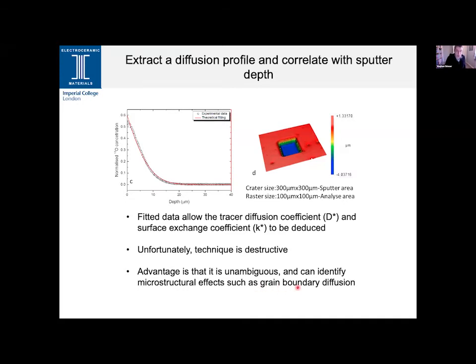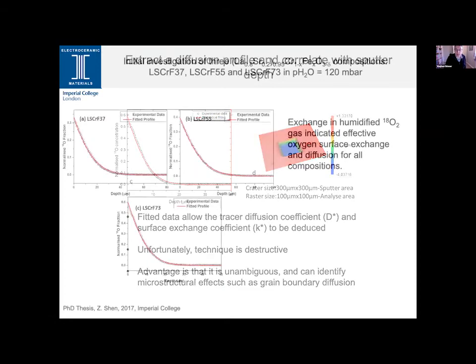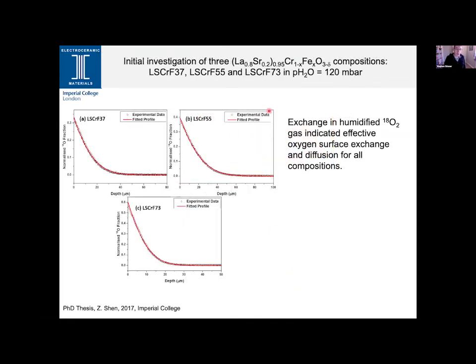So let's turn to some of our initial data on the system. The initial investigation was looking at our lanthanum, strontium, chromium iron oxide compositions. These were slightly A-site deficient with different iron to chromium ratios. So these are the 30% chromium, 50% and 70% chromium compositions. And these were initially annealed in a pH2O of 120 millibars with no oxygen balance.